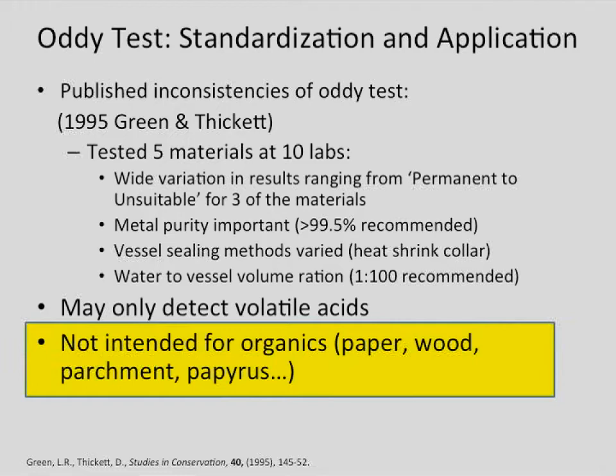Back in '95, Green and Thickett looked at 10 labs. They sent samples, the same samples, around to 10 labs with instructions for how to run an Oddy test so that everybody did it the same way with 5 materials. And they found that 3 of those materials came back with ranges of permanent to unsuitable. So it basically said, well, we aren't standardized.